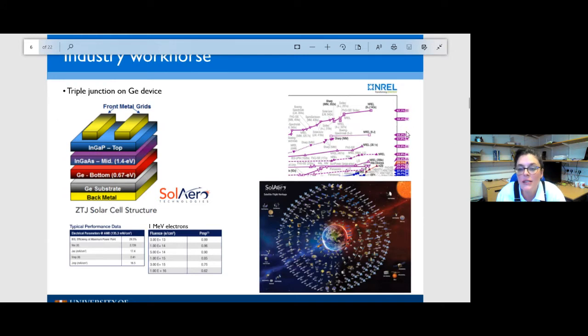this device is very similar to these kind of record 40% plus type efficiencies, but in fact, the efficiencies that we see on orbit will be much, much lower, probably closer to 30%. The reason being that these are terrestrial spectrum efficiencies. The extraterrestrial spectrum has much more IR, and so it's a much less efficient energy conversion. These are also often characterized under concentration, which is generally not the case for space-based platforms. And also, we've got to bear in mind that this cell is actually not designed for peak efficiency. What it's designed for is longevity within the radiation environment, so maintaining a high but level efficiency for the lifetime